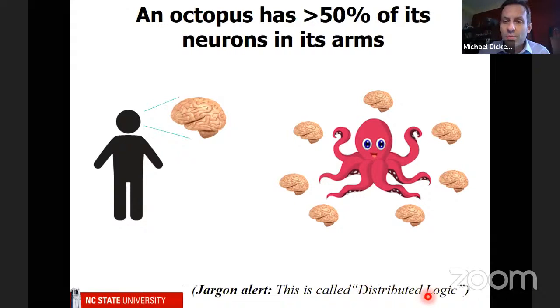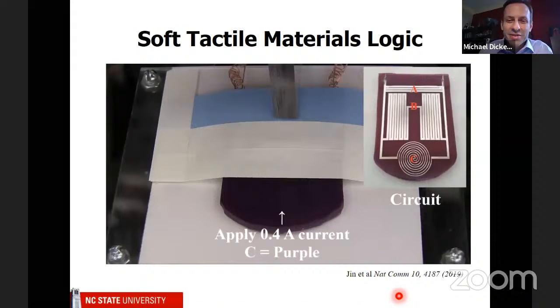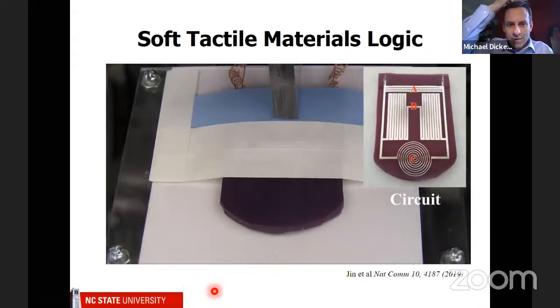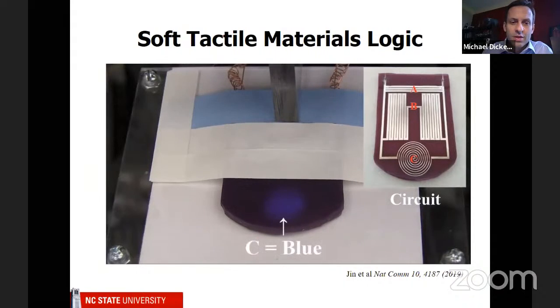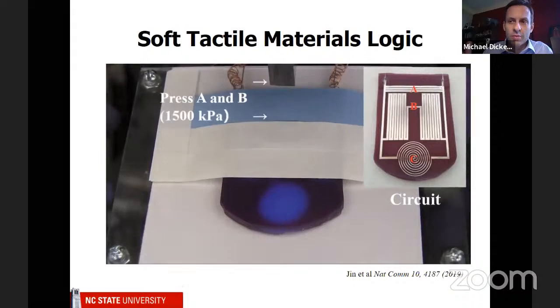So this is sometimes called distributed logic. So instead of having it in a central place, you have it kind of distributed. Okay, so we cannot do this, but we have a very modest step in this direction. So we made a very simple circuit that has A, B, and C. And the current goes through A, B, and C. So if you flip this over, this is region C, and you can see that it looks purple. However, if we come and push in region A, we're going to redirect the electricity so that there's now more electricity here. And so now we get a blue color because it's warm enough that the red disappears.